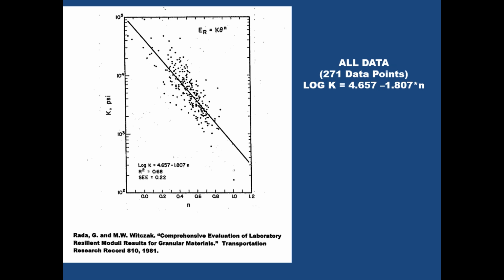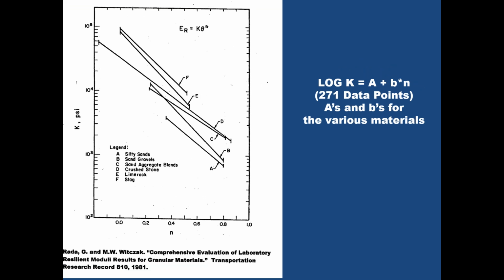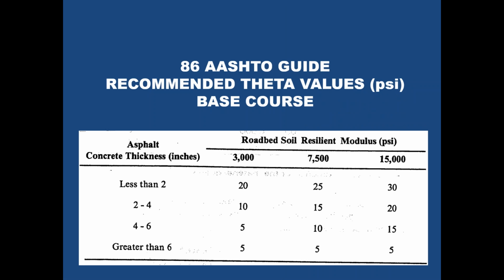This is for all the data. If you look at various types of materials, you'll find that in general there is an effect between silty sands, which are down here, and crushed stones, et cetera, that are plotting up here. But they all have the same general relation: log K1 is A plus B times K2. And thus you're back into this idea of, okay, what's theta? What kind of stress states do we actually develop in a conventional flexible pavement?